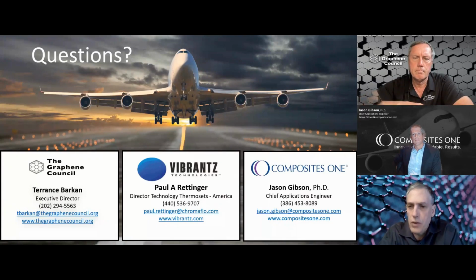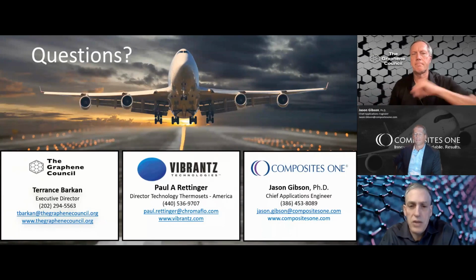Well, we've done some research on graphene as it relates to thermal analysis and thermal performance of materials. Yes, it can increase your thermal conductivity at certain loadings. The threshold's a little higher than what you achieve for mechanical properties. You can achieve a degree of, say, static dissipative conductivity using graphene. Again, the threshold varies a little bit from what you would use if you're trying to achieve mechanical properties. What I think is really interesting, though, is when we've done TGA studies, we've seen anywhere from 5 to 10, sometimes even higher increases in the temperature of onset of degradation. In other words, the graphene seems to behave as actually a protecting material and a stabilizer in some cases for the epoxy resin and or urethane or other materials that we've tested it in.